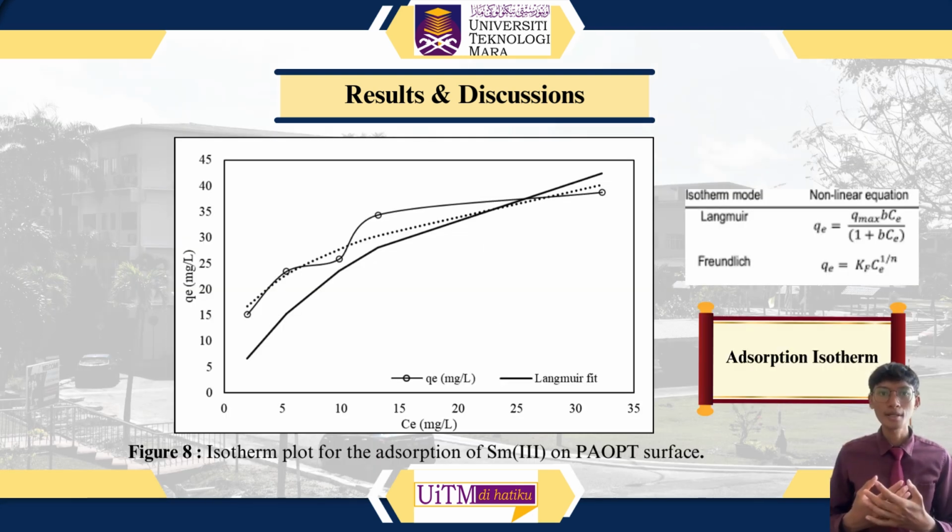By asserting that an increased concentration of samarium provides a driving force to overcome the mass transfer barrier between the aqueous phase and the solid material surface, the elevated correlation values indicate that the Langmuir model effectively characterizes the adsorption process of samarium, suggesting that the adsorption is likely monolayer on the homogeneous PAOPT surface.